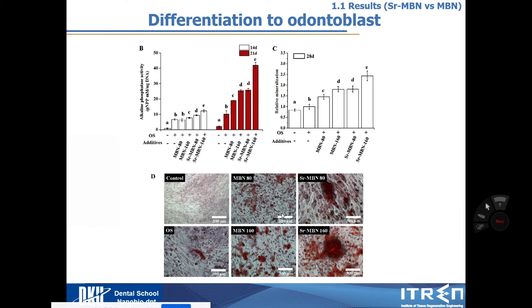So from both assays, I can say that this strontium MBN is better at showing phosphate and calcium deposition on the cell compared to without strontium. So even the bioglass nanoparticle without strontium has a better effect than just normal differentiation media. So we can say that strontium has some synergistic effect to induce osteoblast differentiation from the human dental stem cell.